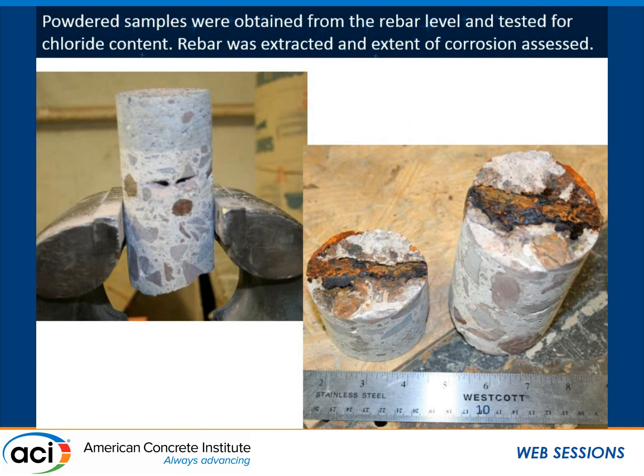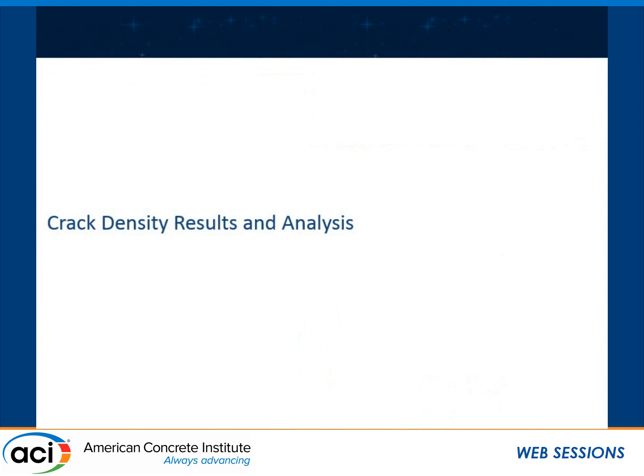We determined the chloride content. We looked at the condition of the rebar. This is probably one of the worst looking rebars that we could find. Fortunately, not a lot of PennDOT decks were in this shape. So let me show you some of the results. First, I'm going to look at the crack density results.